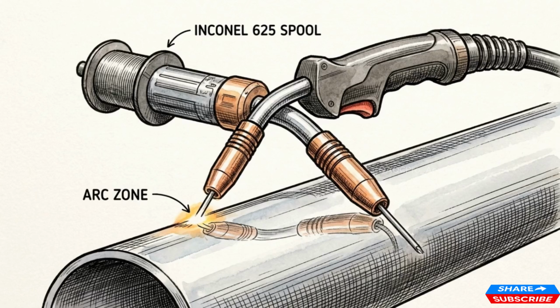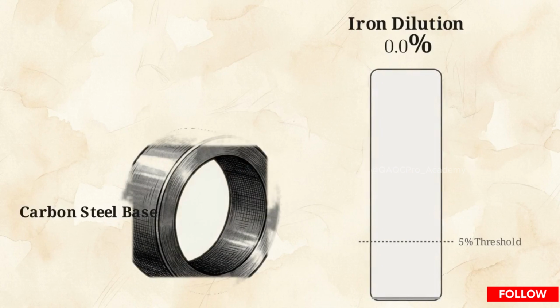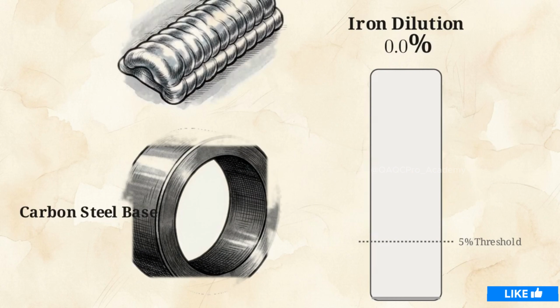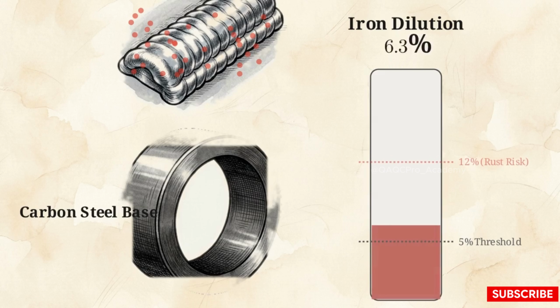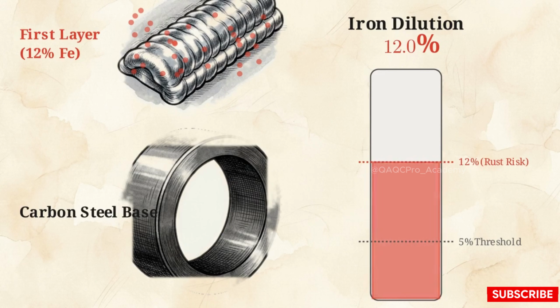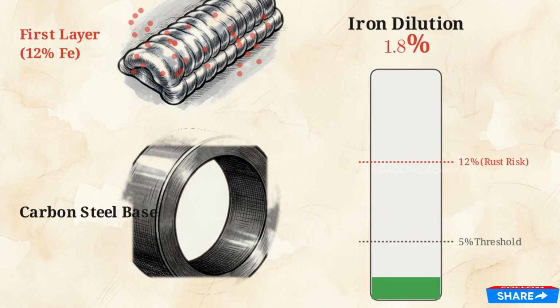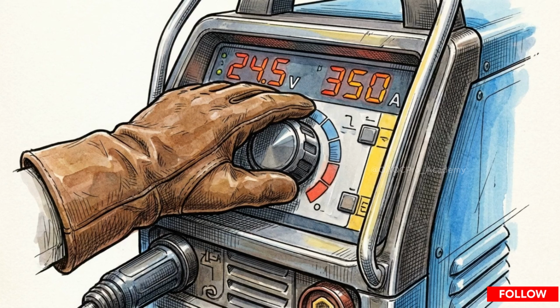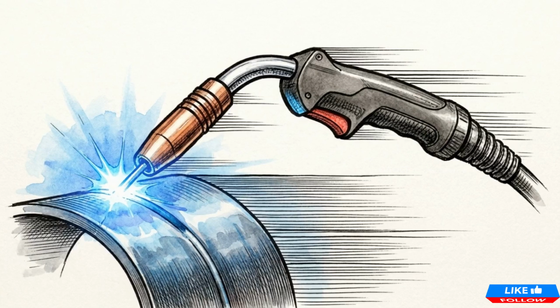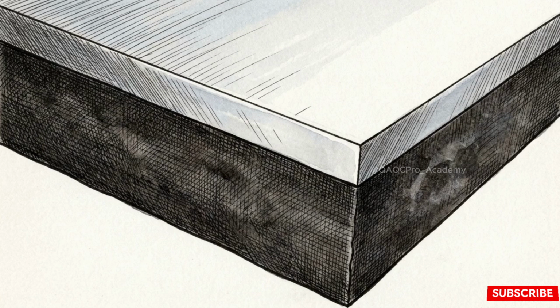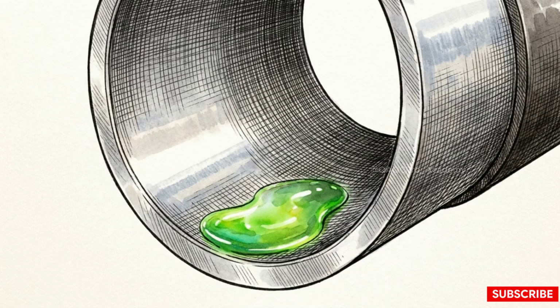Once the surface is pristine, you can begin the gas metal arc welding, or MIG, process using the Inconel 625 filler wire. As you lay down the weld, you must fight a metallurgical phenomenon called iron dilution. As the arc melts the metals, iron from the carbon steel base pulls into the Inconel layer. A single pass can hit 12% dilution, causing rust. Applying a second weld pass caps the contaminated layer, keeping surface dilution below 5%. To minimize this mixing further, calibrate your machine to use lower heat and maintain a faster travel speed during the weld. Precise control over iron dilution is the only way to ensure the Inconel maintains the chemical resistance needed for harsh environments.